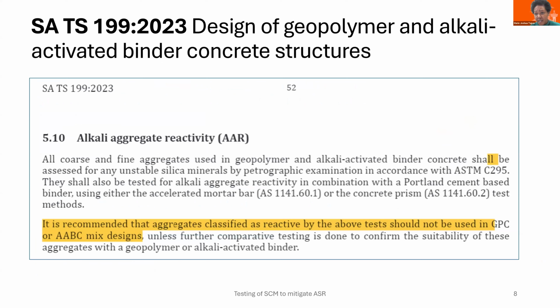Looking at this particular standard on ASR, like any other state guideline, if you can avoid using a reactive aggregate, don't use one. If you have to, it defers back to the accelerated mortar bar test. The criteria are a little bit vague, but it provides an opportunity to use reactive aggregates in combination with alkali-activated binders, provided that the expansion is less than an OPC with a non-reactive aggregate, which means then your system should have no expansion at all to be considered acceptable. So I think there's a potential in there, but it would have to be clarified in terms of expansion limits.